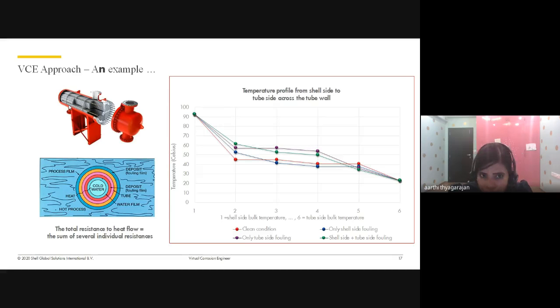This is for one example system, with the process side temperature on the left extreme of the graph to the cooling water temperature on the right extreme of the graph. You can see clearly there are several resistors in series that are playing a role. Now what we did is, this tube skin temperature is calculable by a simple engineering science based model by including energy and mass balance. Combining that with the design data and operational data, we can calculate the corrosion rates, and also we can point out what is the cause of the degradation of these tubes.